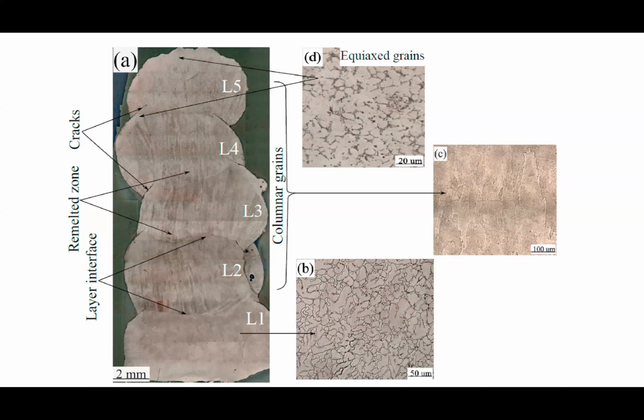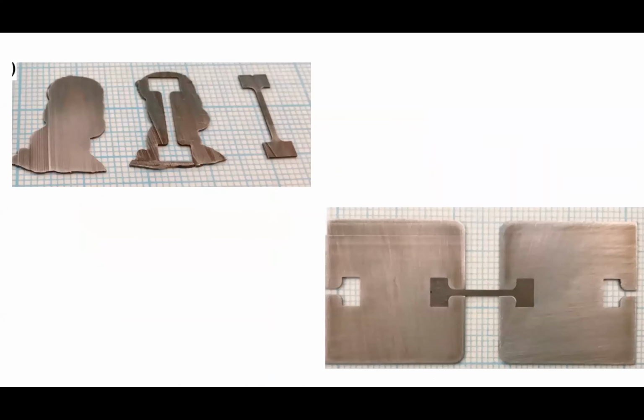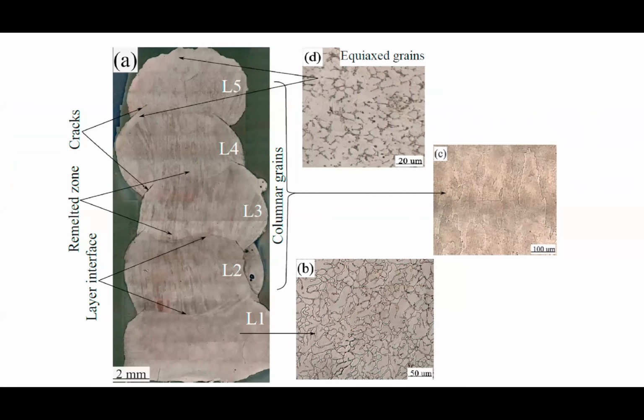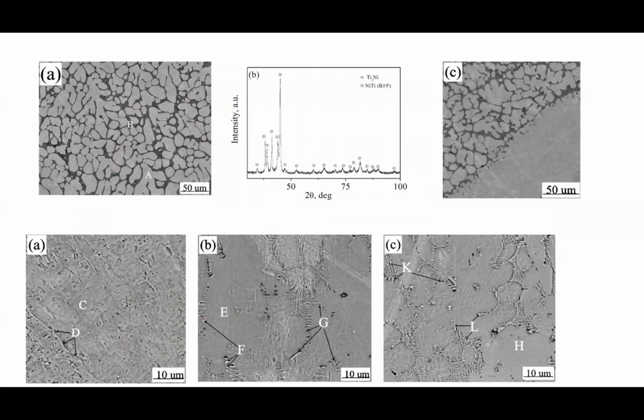Now, when we try to talk about the chemical phase composition of these NiTi structures, basically we took SEM and EDAX analysis, and then we also had some mechanical analysis. So the microstructure and the chemical composition in the different layers of samples were studied with SEM, EDAX, and XRD. In the SEM image of the first layer structure, it has been seen that 2 phases are observed. One is a light gray phase, which is marked as A, that looks like a dendrite matrix, and a dark gray phase which is marked as B, which